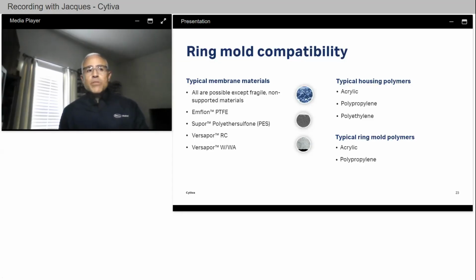Most types of microporous materials are compatible with insert molding. The materials you may want to avoid or just exercise additional care with are typically those without a support, such as PVDF or glass fiber materials. The housing materials that demonstrate the best compatibility with insert molding with these microporous materials are acrylic, polyethylene, and polypropylene.